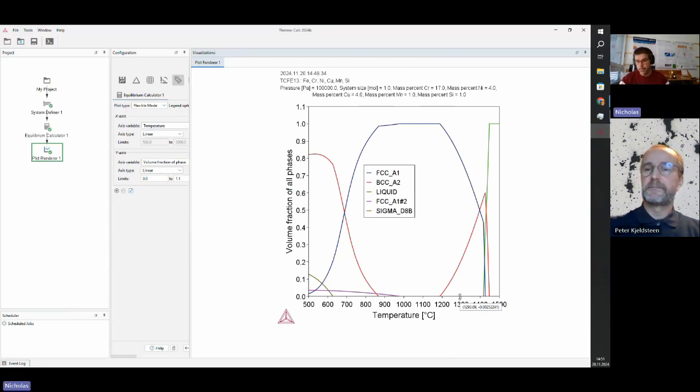Okay, interesting. Yeah. So alloys like the super austenitic steels, 904L types like that, have no delta ferrite. If I sinter that at 1,300, I would get a lot lower densification than I do with this alloy. Okay. That's also a good sign, to see how much delta ferrite I have. Then I know my activity is there. Interesting. I didn't know that. Okay. Yeah.